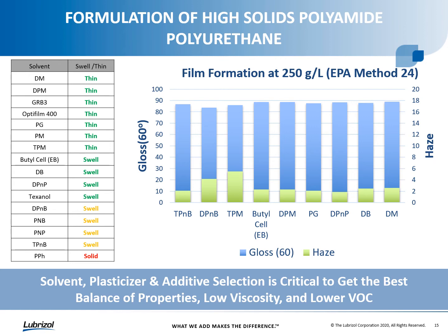And you can see some of the solvents and plasticizers have more of a thinning effect, very good compatibility with the resin. Some of them tend to swell the resin a little bit more, so you see some that are listed in green that say swell. Although they swell or build some viscosity, that doesn't necessarily mean they're incompatible, but they could lead to some potential stability challenges. Then we see some in yellow that are a little less compatible. And the only one in our studies that we found to be really incompatible with the resin was the PPh solvent. But ultimately, the solvent, plasticizer, and additive selection is critical to get the overall best balance of properties, maintain that low viscosity, and get the lower VOCs.